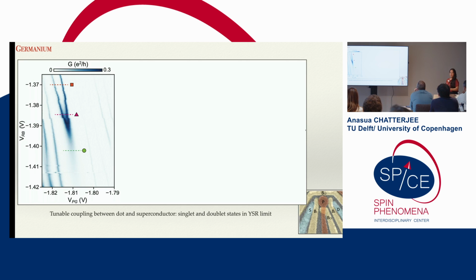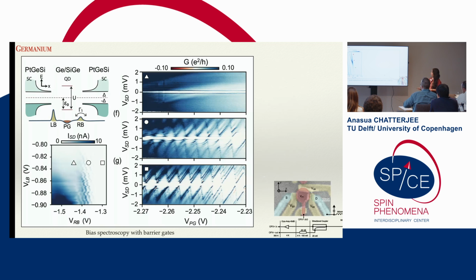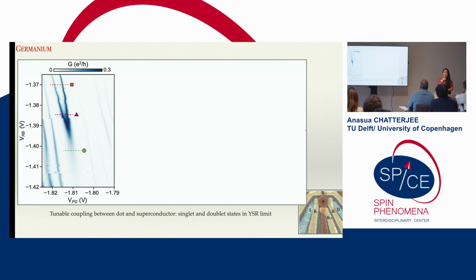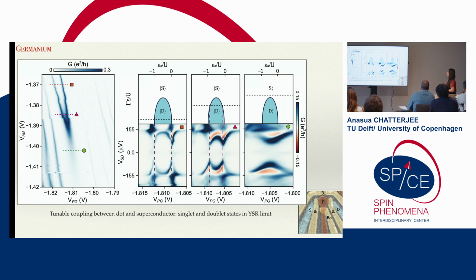The next thing that was exciting and that we can see is that you actually can see the signatures when you turn to this intermediate tunable coupling. You can see signatures of singlet and doublet states, and we believe we are in the YSR limit for this experiment. And so we find this in our plunger gate versus barrier gate space. And we try to tune from the doublet to the singlet, and we believe that's what we're doing. We do some modeling as well, but I don't really show that here.